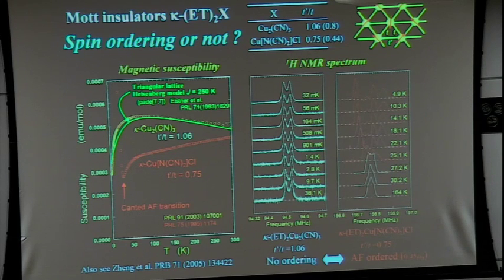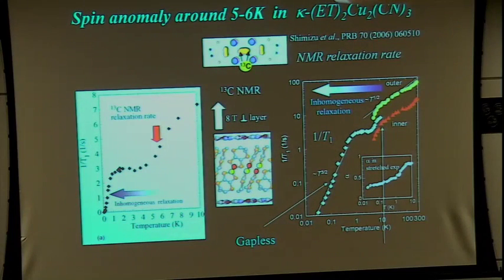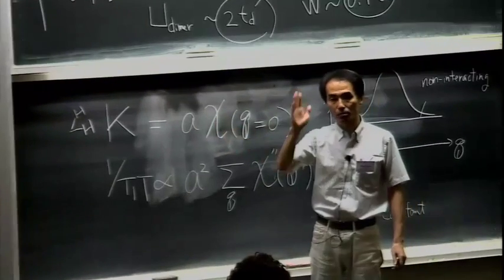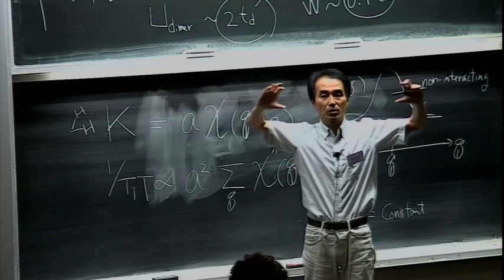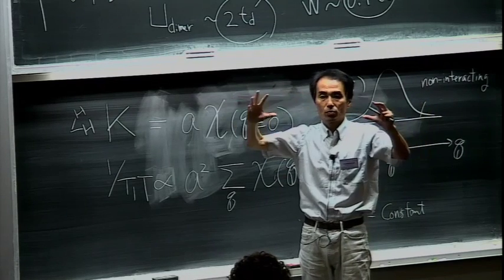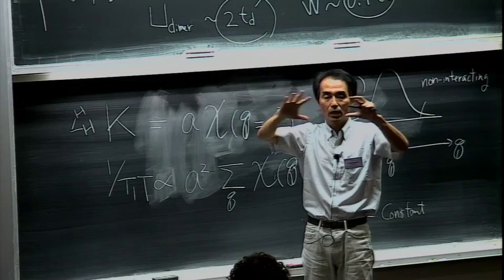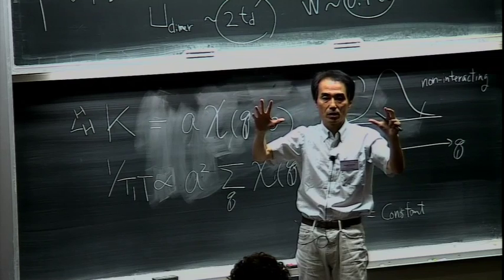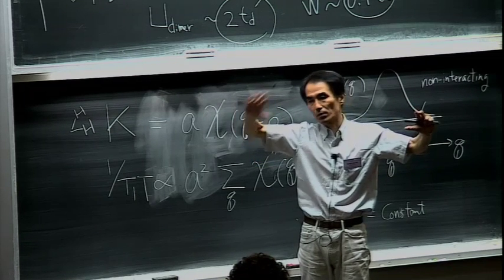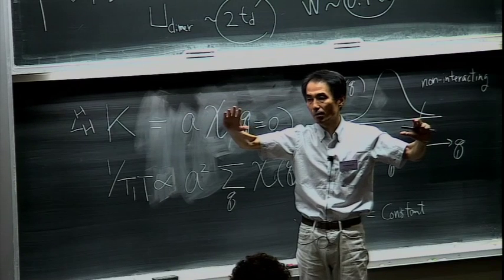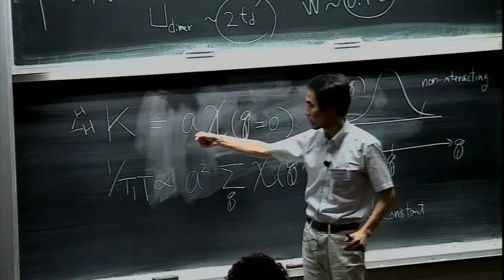So please remember the temperature dependence of the spin susceptibility. The NMR relaxation rate's temperature dependence gives a hint to this puzzle. As I said, the coupling constant is very small at the proton site because the proton is located on the edge of the molecules. The HOMO's spatial profile is centered in the ET molecule, with vanishingly small amplitude at the edges, so the hyperfine coupling constant there is very small.